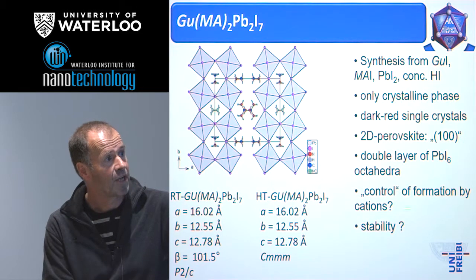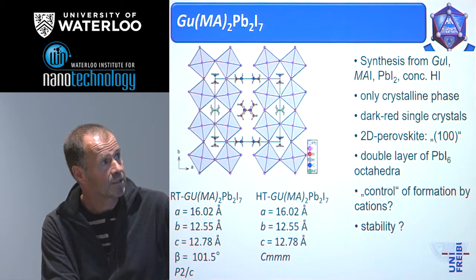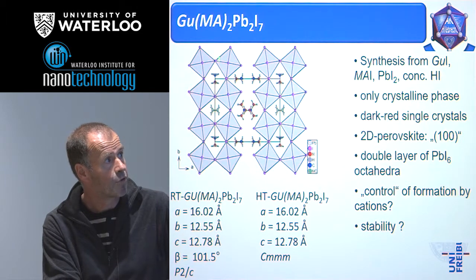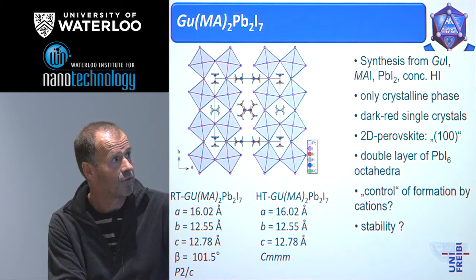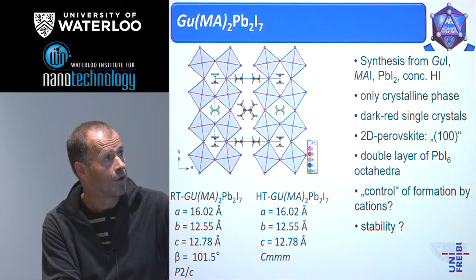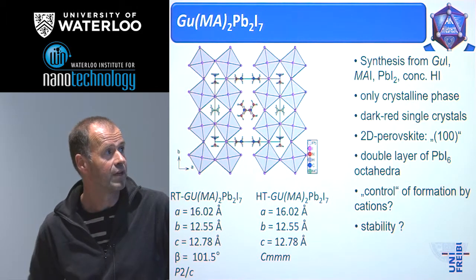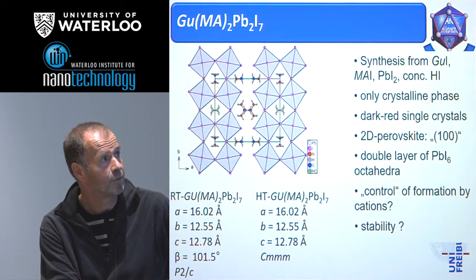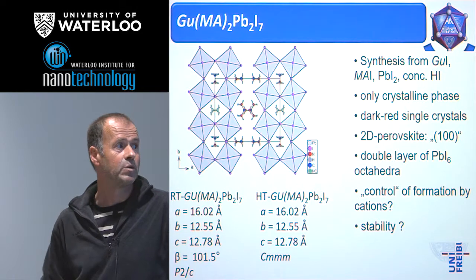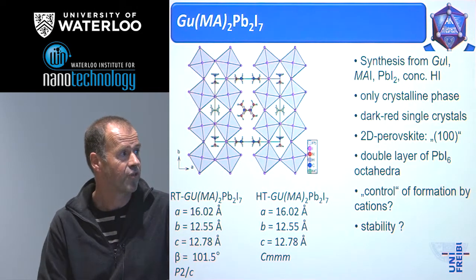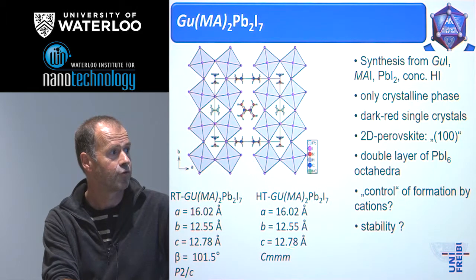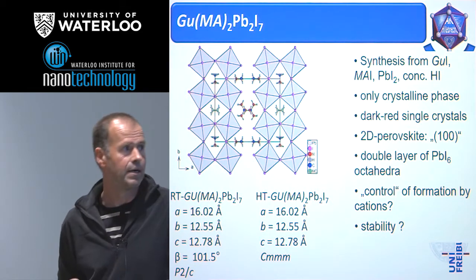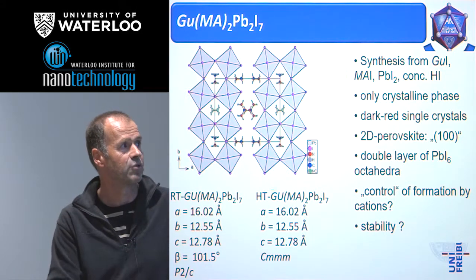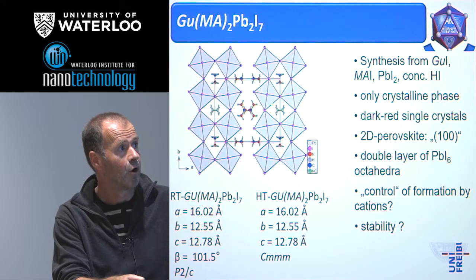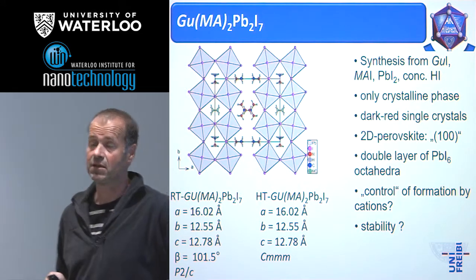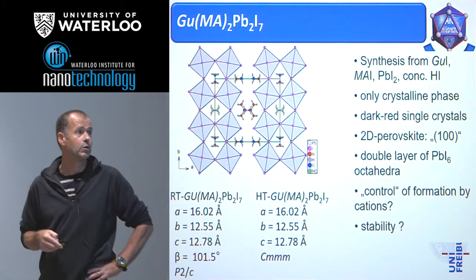You also see from this picture that the cations have an influence on the stability. This is the methylammonium. You see one is oriented in this way, the other here, and the rotation of the octahedra fits perfectly to the size of the voids, and the 2 other cations also fit perfectly. We see that we have 2 different modifications. There's a room temperature form and a high temperature form. The high temperature form is more symmetric as we know it, and it depends on the rotation of the organic cations, and the stability is better than for the normal methylammonium lead iodide.